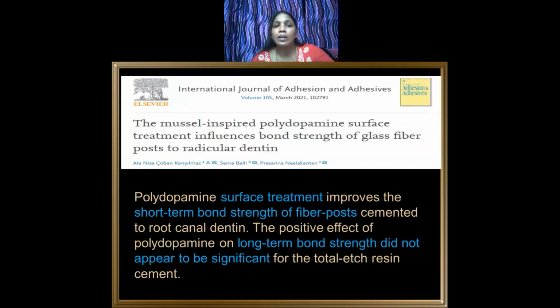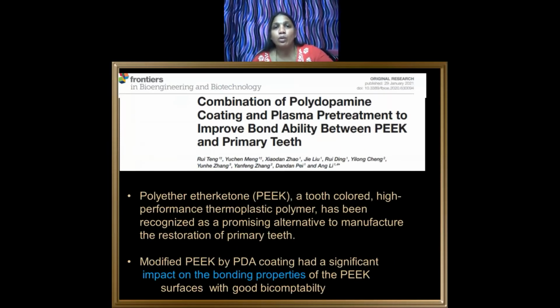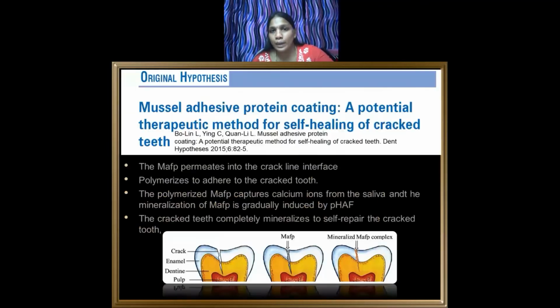And Prasanna et al. have used this polydopamine as a surface pretreatment for the post surface in order to increase the bond strength between the post and the root canal dentin, which they proved improved both short-term and long-term bond strength. And combining polydopamine coating with PEEK crowns, which are tooth-colored high-performance thermoplastic polymer crowns for primary teeth, had a significant impact on the bonding property, with good surface adhesion and good biocompatibility.